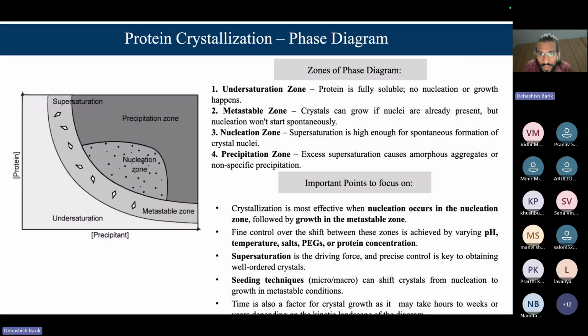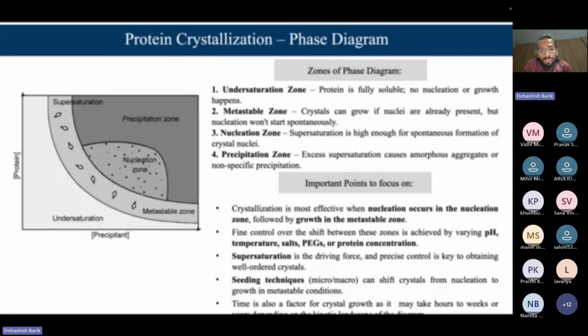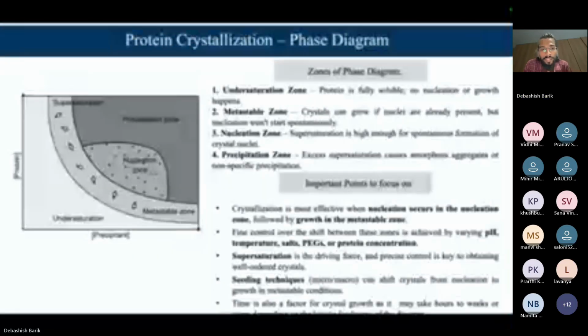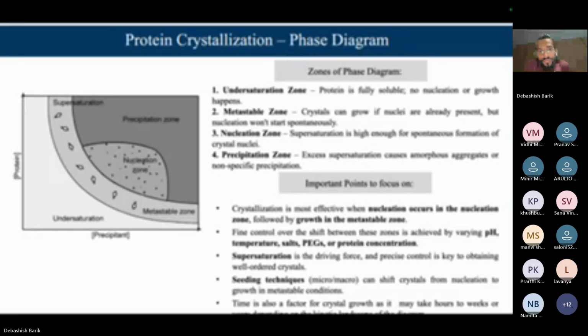Then there is the metastable zone. Crystals can grow if nuclei are already present, but nucleation won't start spontaneously. If crystals are already grown and we put that grown crystal in this particular zone, the metastable zone, then it will grow. Otherwise, the protein will not grow in this zone. Then the nucleation zone. This is the zone where the crystal nucleus actually forms. So supersaturation is high enough for spontaneous formation of crystal nuclei. Once the crystal is formed in the nucleation zone, if we put those crystals in the metastable zone, then these crystals will be able to grow. But nucleation occurs only in the nucleation zone.